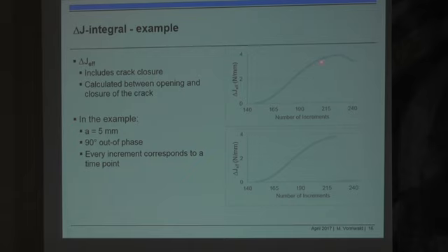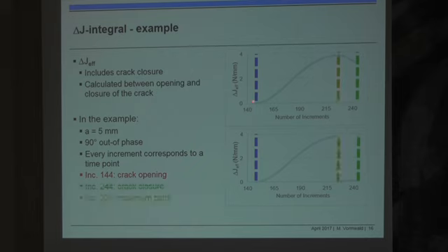Then we trust them. In these cyclic cases, you arrive at a maximum, and then the cyclic J integral goes down, and we say that the range of the J integral is then from here to there. Finding this initial point was not so difficult. It is always somewhere around where the crack opens. As soon as it is completely open, or slightly before or after that point, you get increasing J integrals until you get some decreasing value.